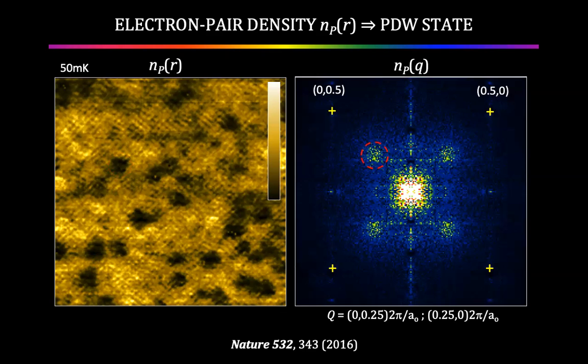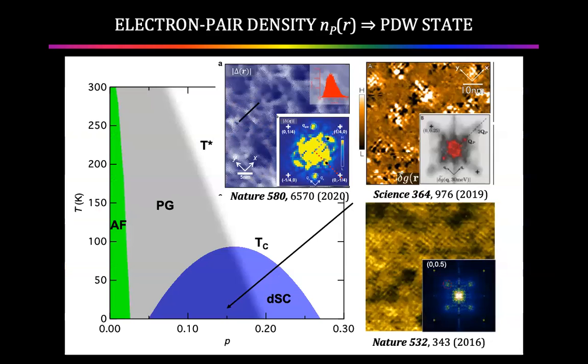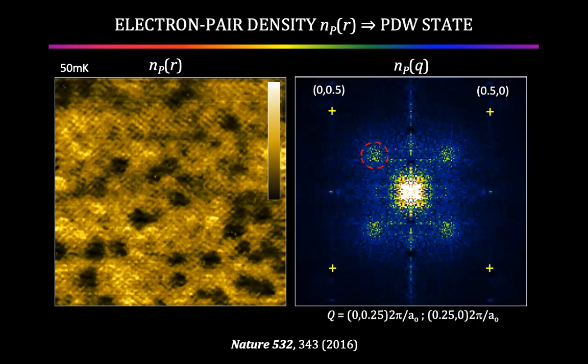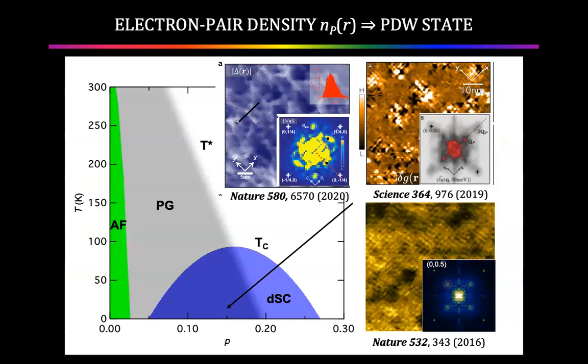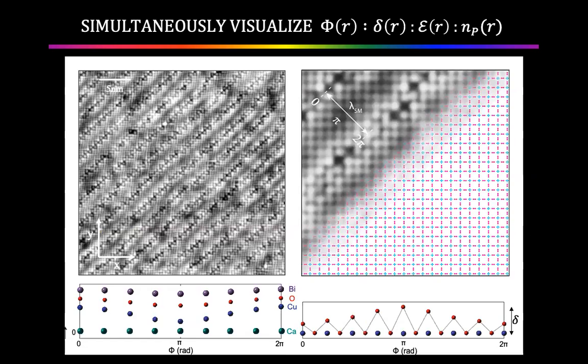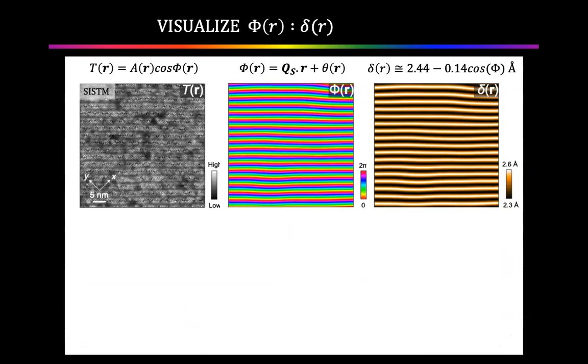So imagine we're imaging the density of pairs. One of the things we found is that there's a pair density wave, but I'm not going to discuss that today. There is a pair density wave in cuprates. So by using this technique, we can tell what is the apical distance. So here's a real surface. We measure the modulation of the surface, assign it a phase, okay? And from the phase and from the X-ray refinement, we assign an apical displacement everywhere in that field.